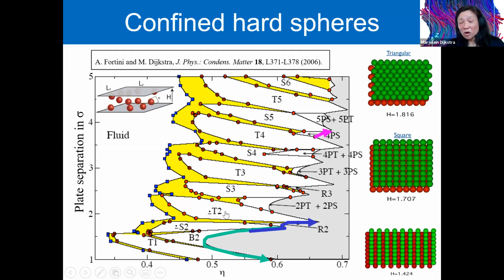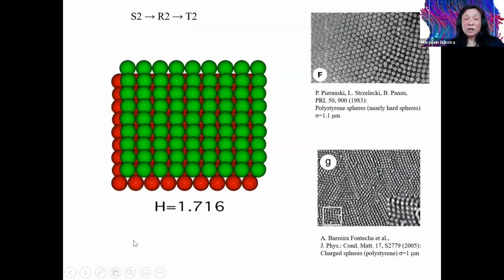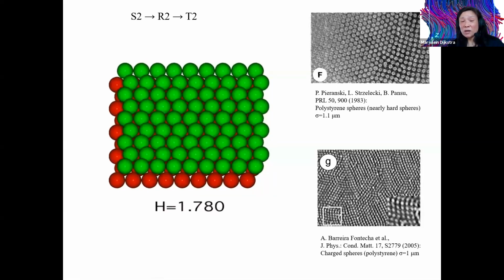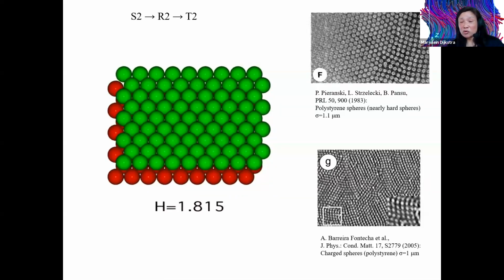One can also take an opposite path, so we start with two square layers and then increase slightly the plate separation so that we take a path at these maximum packings. And there's a rhombic phase, and then it goes towards two triangular layers. And that's shown here. It starts to buckle, and then in the end, it forms two triangular layers. And all these structures were also found experimentally in polystyrene spheres, but also in charged spheres.